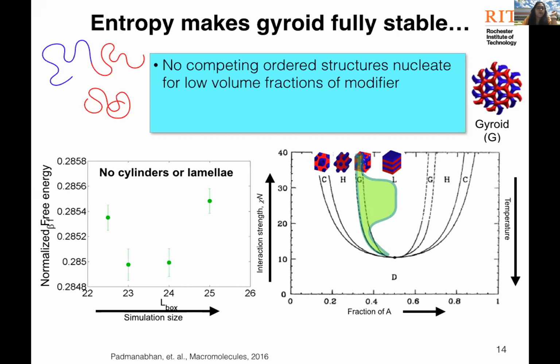We can also infer the ideal unit cell dimension. Here that's between 23 and 24 sigma. So the thermodynamic integration method is just a little bit better. Now you can see the error bars are smaller, and you can actually see the difference between the stable phase and the other one.